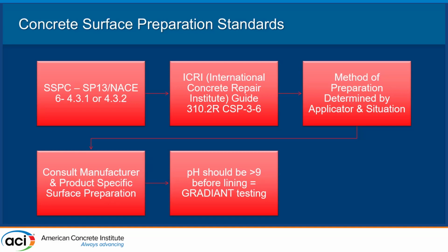And then we always recommend doing a pH test to make sure that the concrete is suitable for coating, because the acid attack, whether it's environmental carbon dioxide or in a situation where you have acid contamination, will lower the pH to the point that if you coat over it, that deterioration will continue to happen after the coating.